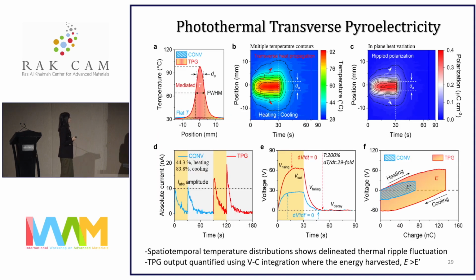So here, the temperature profiles of a TPG show a 200% increment in the temperature harvesting, as well as up to 29 folds in terms of heat variation harvesting. That's nearly 2 orders of magnitude, or about 2 orders of magnitude.